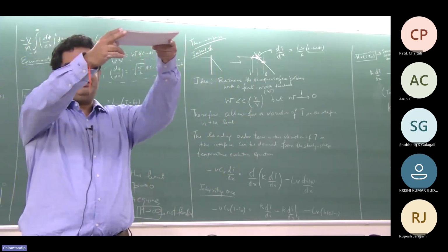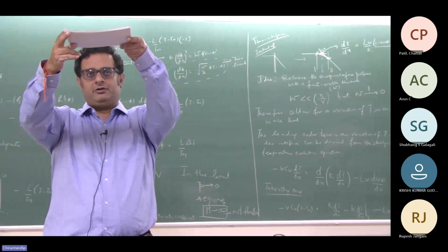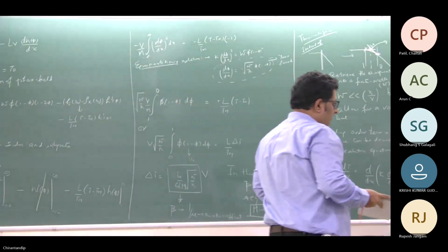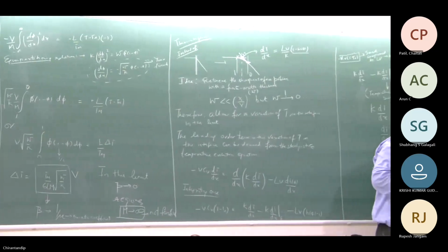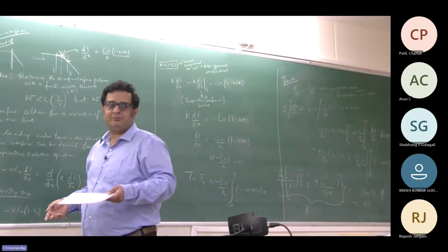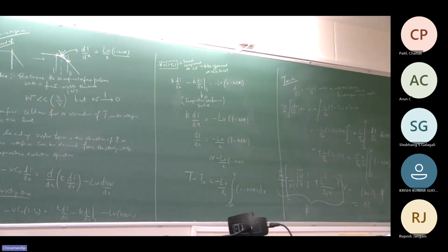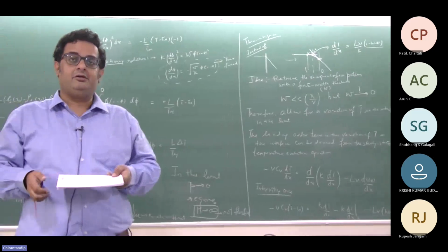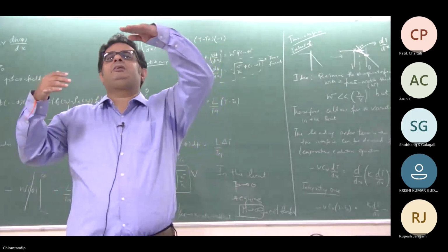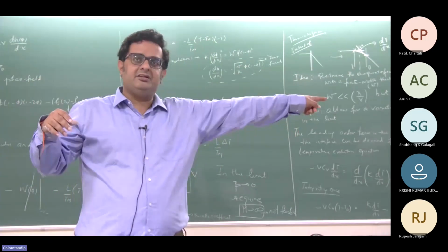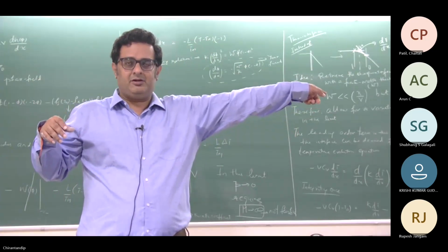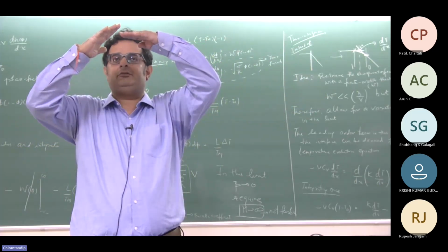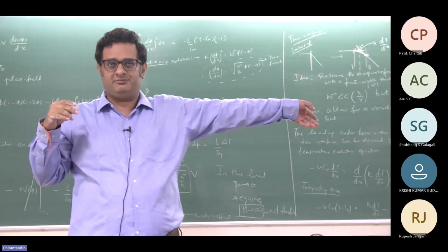Okay. What is this composition that it settles down to, given a velocity? Typically, if beta is 0, that composition will be the equilibrium composition from the phase diagram. Now, what happens if there is solute trapping is that this derivation is no longer possible, because your asymptotes from both sides are not really the same, so you can't write down an effective beta expression.